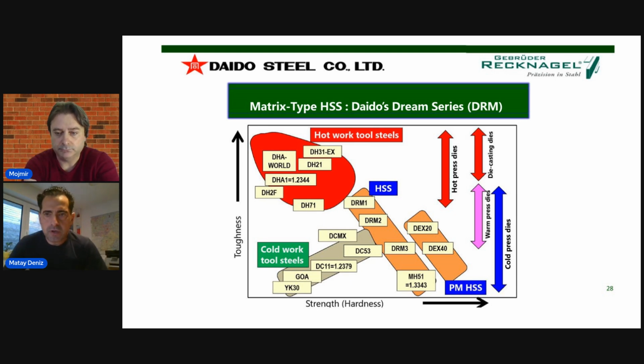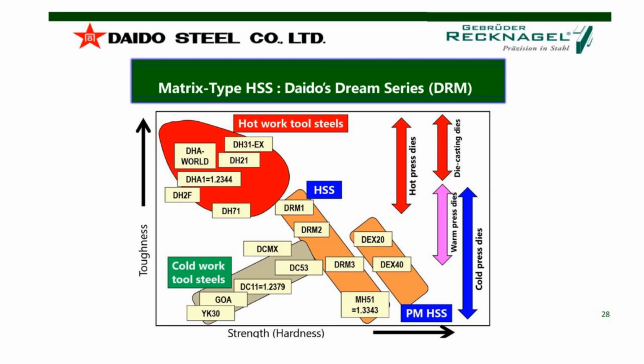So let's go into the Dream series. What about the positioning of the Dream series? The basis is the M2, meaning 1.3343. You can see the M2 positioning in the orange area, and this is the basis for the Dream series. The Dream series is in general a modified 1.3343. The Dream 3 works very close to the hardness of M2, that means a hardness up to 66 HRC, but the toughness and the pressure resistance are much higher than with M2. The Dream 2 is a little bit closer to the DCMX. You can see the hardness is very close together.